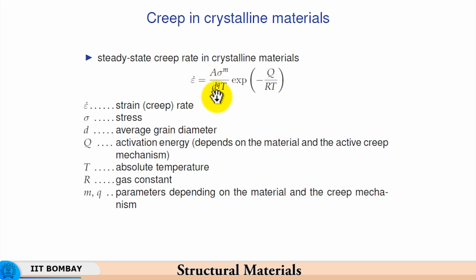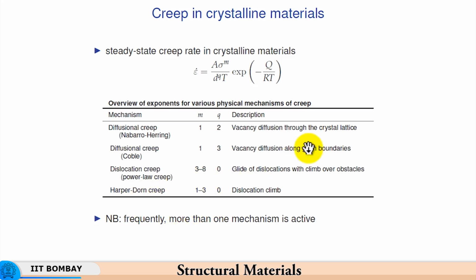So, the smaller the grain size, the larger the creep strain rate. That is the reason why we would like to make the grain size as large as possible, to introduce as slow a strain rate as possible. So, depending on the mechanism, we have these constants m and q. So, diffusional creep, Nabarro-Herring creep, is the creep deformation that takes place at very high temperatures, and so the proportionality is inverse to the square of the grain size. So, it is inversely proportional to the square of the grain size, and also from low to medium level of stresses is something that you can expect